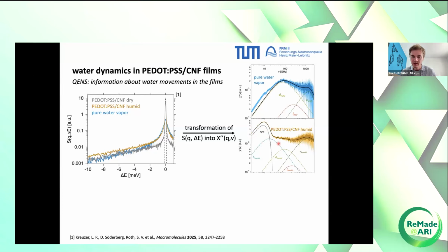And then we see a second peak appearing, also at low frequencies, meaning slower than the diffusion of water. And this we also ascribe to diffusion of water, but of a different kind of water. So we actually have two water kinds in these films. Let's call the one type bulk water, even though technically water in a film is not bulk water, but for the sake of clarity, let's call it like this, which is surrounded only by other water molecules and is far away from the polymers. And we have hydration water, which sits in the hydration shell of the polymers, very close to the polymers, tightly bound, and therefore it's moving on a different time scale. It's moving slower, and therefore appearing here at lower frequencies. So two types of water with different motions.